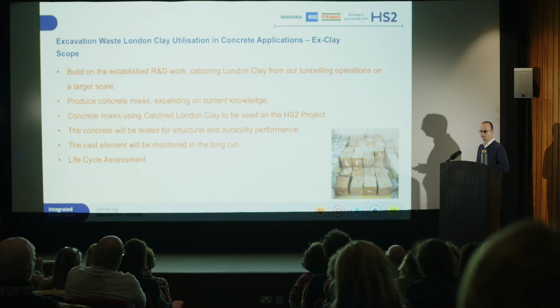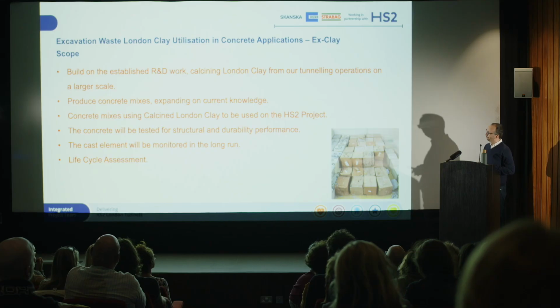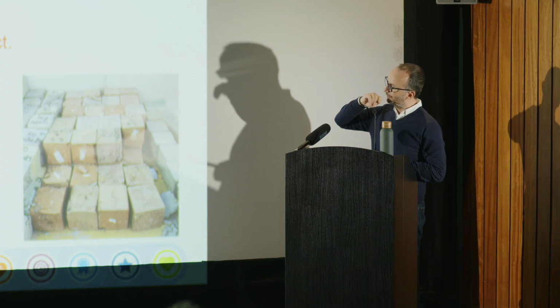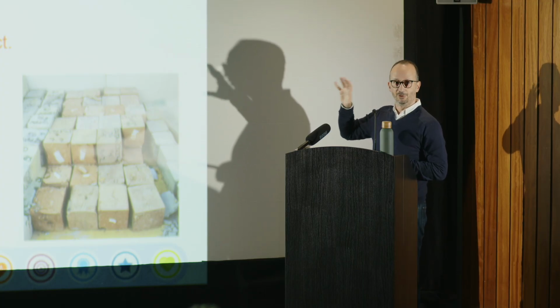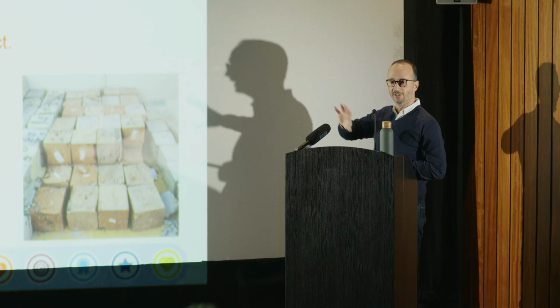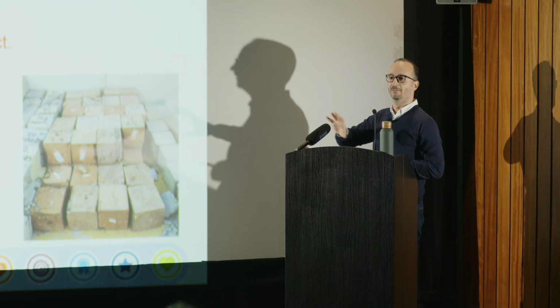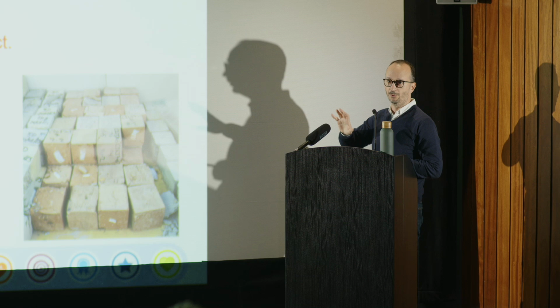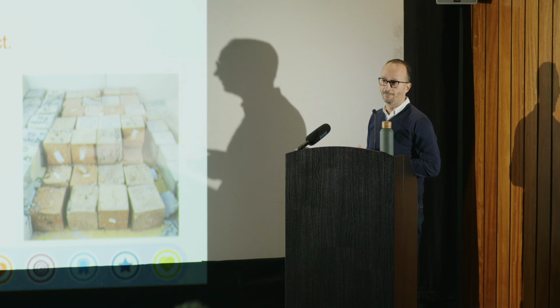And like I said, the carbon footprint of transportation to Denmark coming back destroys every other effort. And just to say on the carbon footprint, when you dry a clay from 40% to less than 5 to go in the kiln, that is the highest energy that you will use for carbon footprint wise.